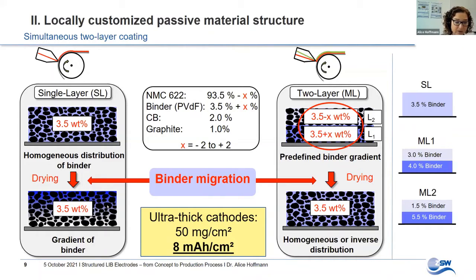To counteract this, two different suspensions can be applied simultaneously with a double slot die on a collector foil. In the experiment I will show on the following slides, the lower layer contains a higher binder content than the upper layer. And on average, they have the same composition as a single layer electrode. In this case, during the drying process, a more homogeneous or even an opposite arrangement of the CBD can be reached.